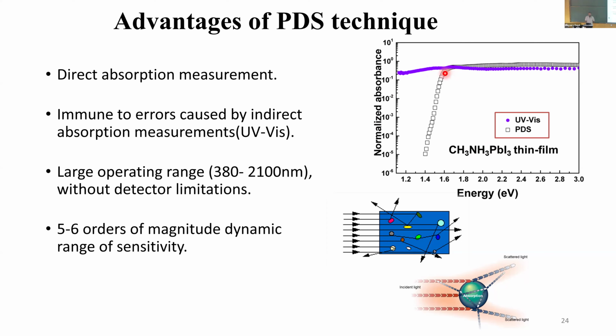Now here I have plotted on a log scale to show what is the difference between the two. Here you see a small bump, but it sort of plateaus out. But with the PDS, what you see is you can go down almost 6 orders of magnitude. And why this happens is because PDS exclusively looks at the heating, and heating only happens when you absorb.